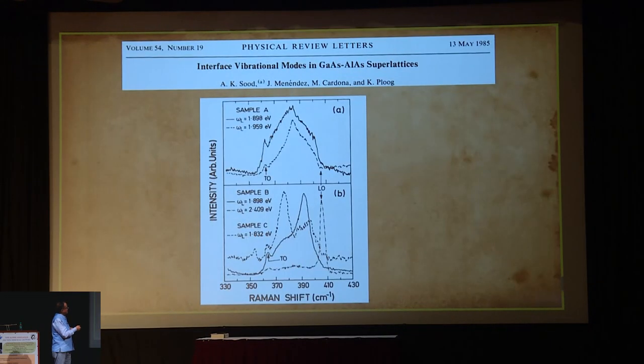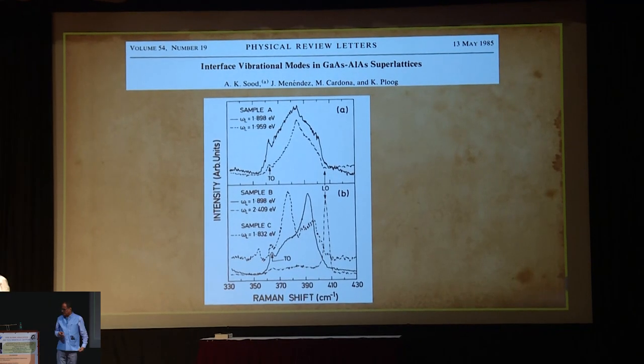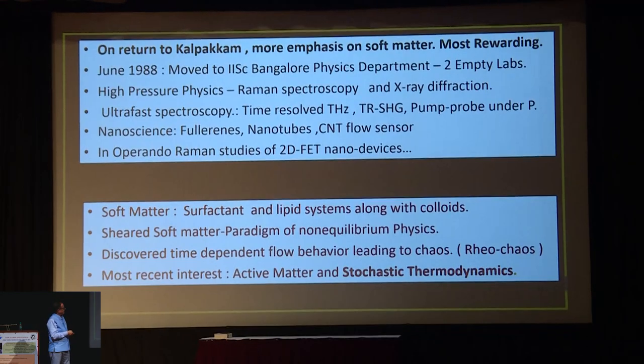And back to back, which I understand has never happened in PRL, we had submitted two papers, 4 pages each. The second paper was on the interface phonon, which only exists at the boundary between the two semiconductors. This was called interface phonons. Of course, we then had a large number of citations, and this field has thrived from that time onward.